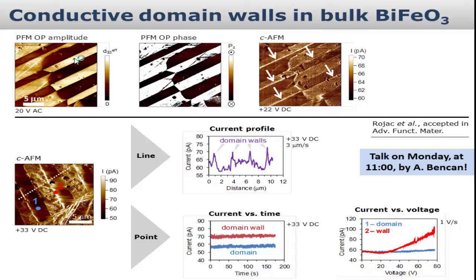One is, as I said, to scan and see if you have a spike when you cross the domain wall. Sometimes one must be careful here, because the field that you apply may at the same time move the domain wall, and that can give you a transient displacement current. So this is checked by sitting with the tip for a very long time, measuring the current, and we were always able to see that there is current at the domain wall which is higher than inside the domain, which tells you that it is probably related to the higher conductivity of the domain wall itself. And there are some other ways.